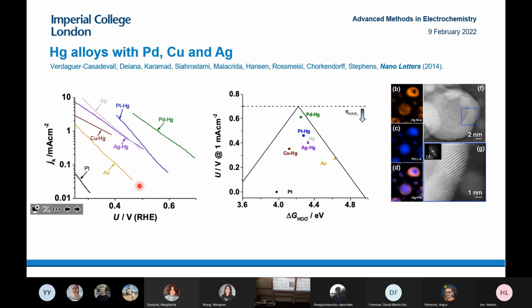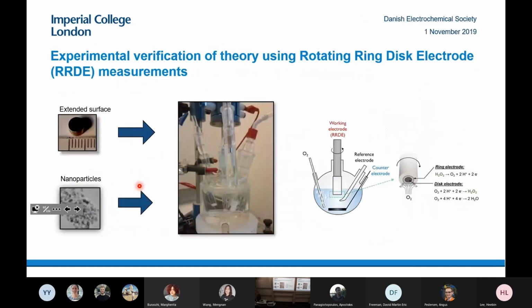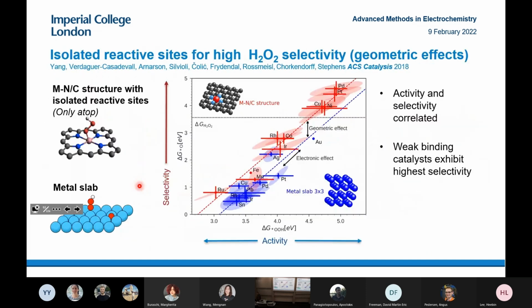As I mentioned previously, probably what's controlling selectivity is the difference between oxygen binding energy and the free energy of hydrogen peroxide. The free energy of hydrogen peroxide depends on the concentration of hydrogen peroxide. So we found that a lot of the catalysts, imagine if you have a very open structure, then hydrogen peroxide will get away from it very fast. It might have a higher selectivity than if you have very narrow pores, for example. That was a nice thing about doing it on a model surface, a planar surface: we don't have those effects. But obviously, a real surface is 3D.